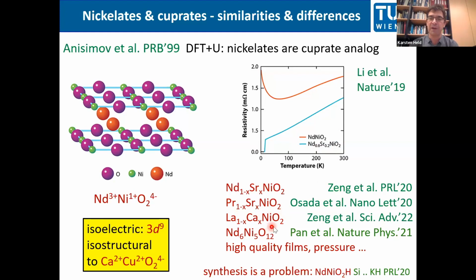So it's a complicated process. You first grow a film with a pulsed laser, and you get rid of oxygen, and you can easily have some excess oxygen or excess hydrogen, as we have looked into here, in your system. And then the system just isn't superconducting anymore.